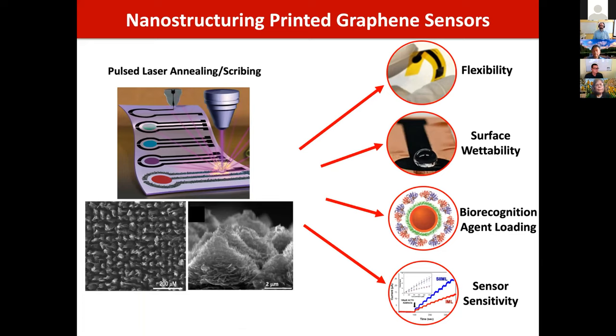And that allows us, if we do it right, if we pattern it correctly, to change the surface wettability from one that's hydrophilic to one that's super hydrophobic. And that hydrophobicity could be important for ion selective sensors. As you put that ion selective membrane over it, we don't want a water layer to build up underneath, or we don't want it to foul underneath. And this improves the sensor stability and prevents drift.